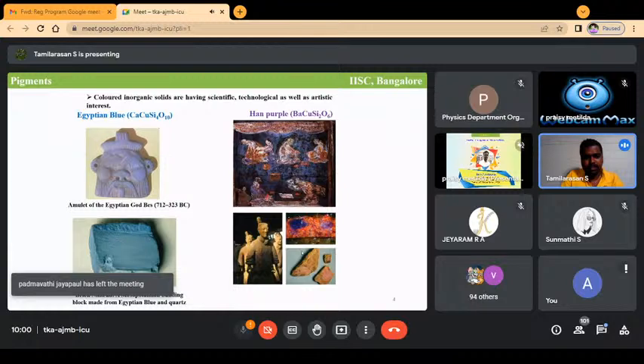So why is this happening? When we look closely at the structure and environment, it's the same 5-coordinated environment. It's trigonal bipyramid. But when we look very closely, these 3 equatorial bonds are almost similar as in the indium compound, but the axial bond is smaller than in the indium compound, which means the chemical pressure is more, and that gives rise to the difference in the color and eventually in the band gap.